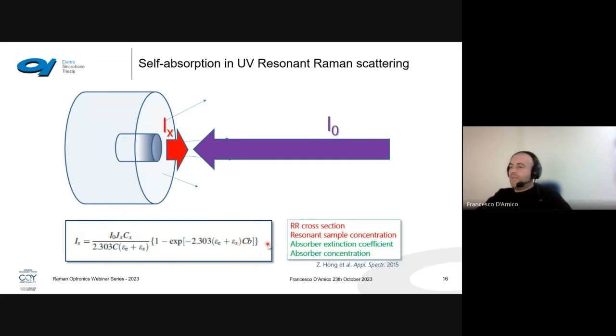So in this formula, we have two terms. We have terms that increase the signal, such as the resonant Raman cross-section and the resonant sample concentration. The higher the sample concentration, the higher the signal, of course. But the problem is that we also have parts that contribute to decreasing the signal, such as the absorber extinction coefficient and the absorber concentration. So the equilibrium between these two parts determines the amount of the exit radiation. And we must take care, because if the absorption is very strong, it means that we can have photodegradation.